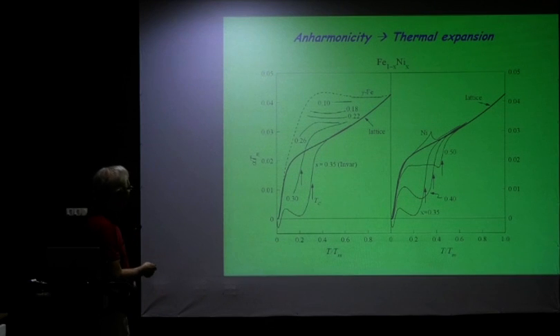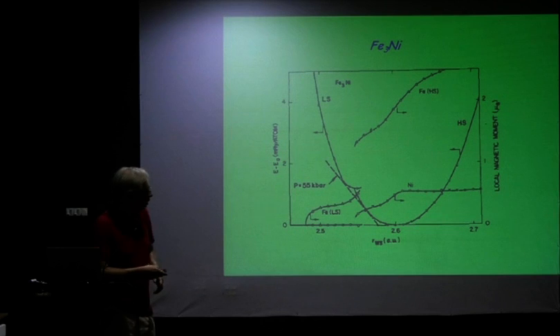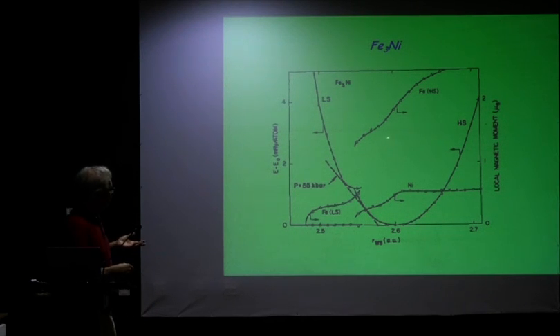And when you look over here, this is this particular alloy, somewhere in between here, and you find these crossing effects of the energy-volume curve also in those compounds. So this is also descriptive of the alloy. So what do we see here? We have an iron nickel. That's again our volume, and this is the binding energy. And we see here that at equilibrium in this particular alloy, we have a high spin state.